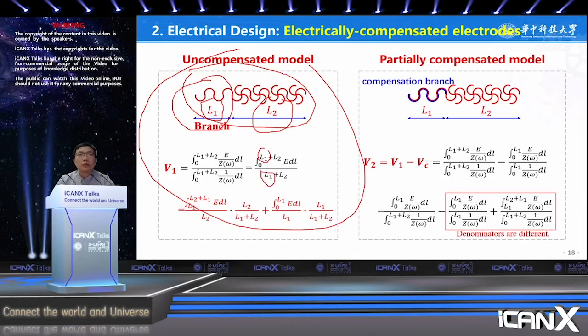In order to reduce the effect of the part L1, the simplest method is to adopt another part that is the same as part L1 and put it along with part L1, like this one, the blue one. We call it the compensation branch. So one can get the partial compensation mode. It's equal to V1 minus Vc. It's a little pity that the two denominators are totally different. So one cannot completely remove the effect of part L1.